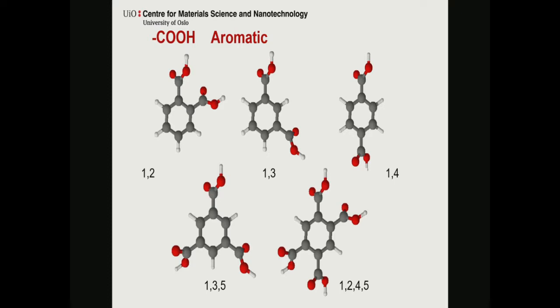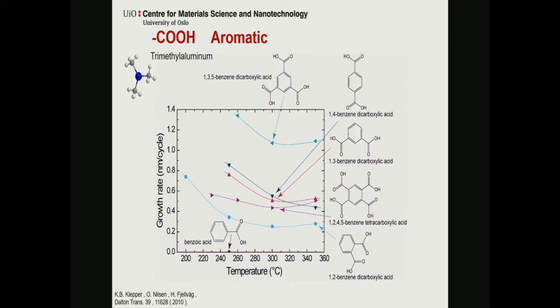So we played around with different sort of aromatic type of molecules, this here, and by doing the aromatic molecules you do get, look at the scale here. This is no longer Ångström, it's actually nanometers. So Christoph, when you talked about the growth, this here can actually enhance your possibilities greatly. Now we're up a factor of 10 in growth rates versus normal inorganic growth, and it can scale with the number of carboxylic acids, not necessarily so.